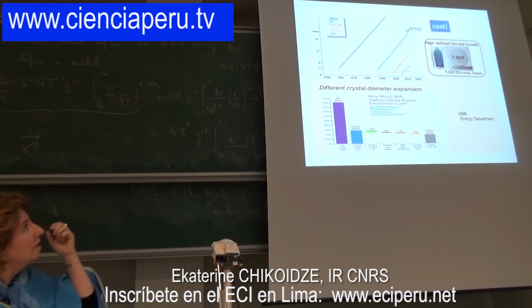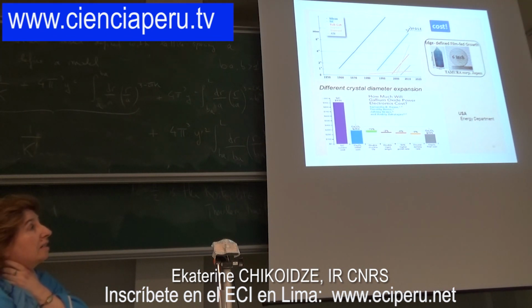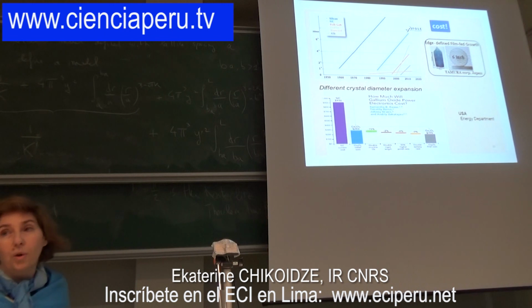And here is Yole's company, a very nice representation of how crystal diameter expands versus years. You can see, for example, diamond is still below 1 inch wafer, and gallium oxide is up to 8 inch already. Diamond has had more than 20 years of huge effort, but is still below 1 inch, whereas gallium oxide, people started working on in 2012. Here I mentioned 6, but in fact there is 8 inch already in Japan.